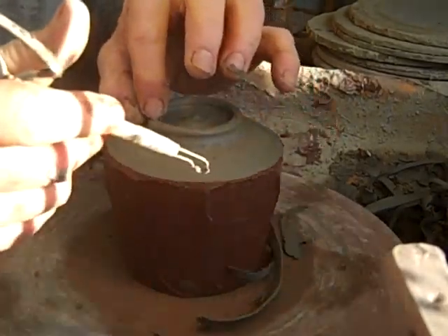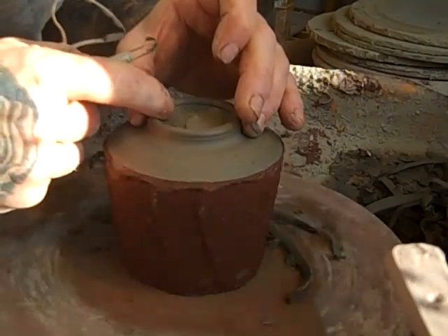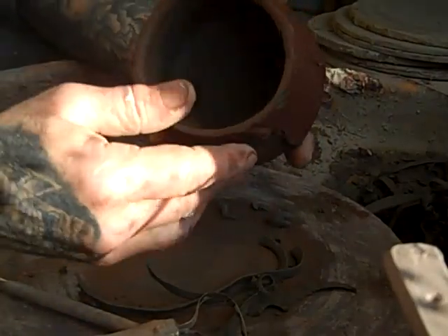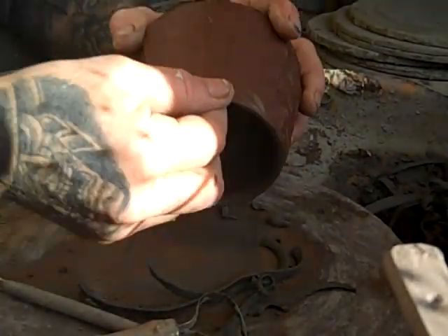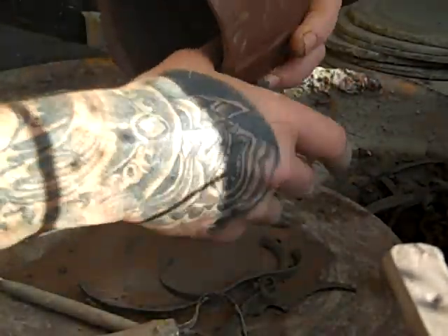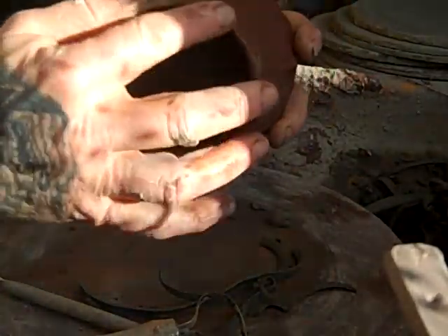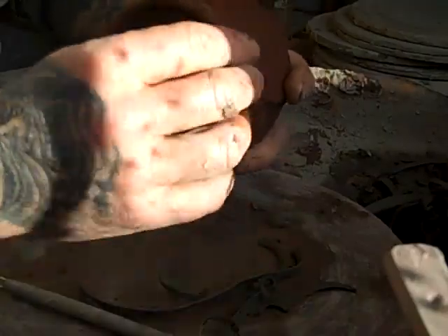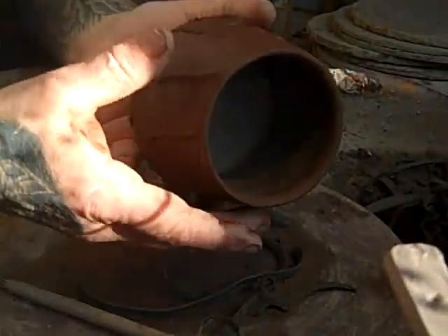As usual I round it off with my fingers. This causes a flat edge on the rim so you just have to redo it so that it's rounded and not a square sharp edge - there are two reasons for that: it doesn't look very good, and also the glaze I use has a tendency to split. If you give it a chance to split it will, because it's a heavy glaze and it sags. So just round that off.